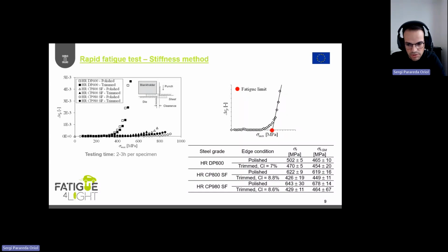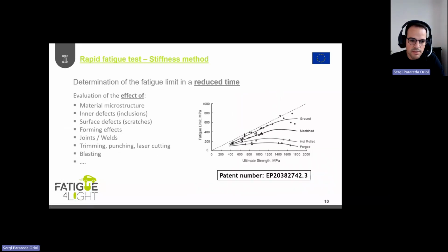And here you can see the results. For instance, the left column is the fatigue resistance obtained using the staircase method, so the conventional method. And in the right column, we have the fatigue limit from the stiffness method. And we can say that the results are quite similar, and the reduction of time is very relevant. So the good point, as mentioned, is that by using this method, we can determine the fatigue resistance, the fatigue limit, but also the slope of the SN curve of different materials, while considering different effects: the microstructure of the material, some defects, forming effects. We also evaluated the forming effects in the project, yes, the trimming and punching, as mentioned.